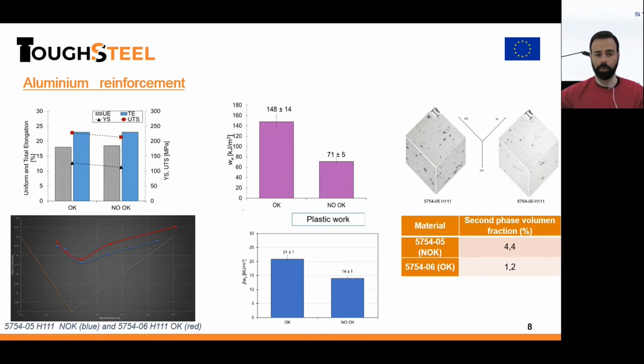We go ahead with the investigation, taking into account the mechanical properties. In terms of yield, tensile, and elongation, the two alloys are completely comparable. We didn't find any big differences in these properties, and also considering the forming limit diagram, in blue is reported the not okay material, so the material that caused the failure, and in red the new material with the changed chemical composition. The FLDs are different, but not so much.